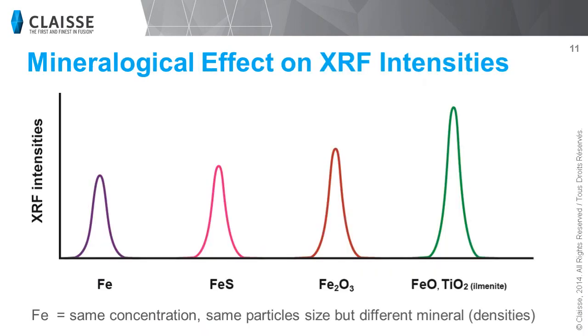Now take a look at this graphic that illustrates the mineralogical effect. We can see here how the XRF intensities are affected by the different mineralogy of iron in press pellet. Also, in natural materials, the composition of mineral deposit varies from one location to another. There are also substitutions of various elements such as contaminants in the crystal structures. Consequently, it is almost impossible to closely match the matrix of standard to unknown using the press pellet technique. Therefore, highly accurate analysis at high concentration levels are difficult or simply impossible to obtain for many natural materials.